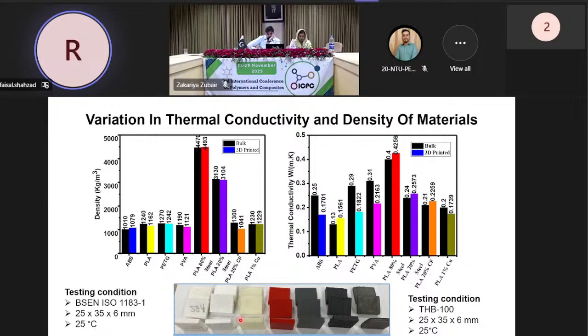So you can see the samples. We have not put the whole battery pack, we just take 25 by 35 by 6 mm samples. We have printed the samples, and then we have measured the density and the thermal conductivity of the materials.